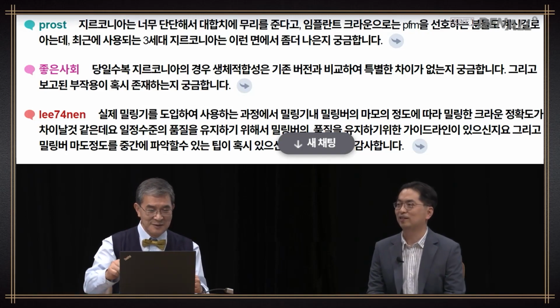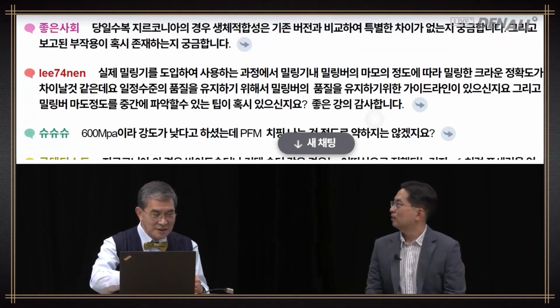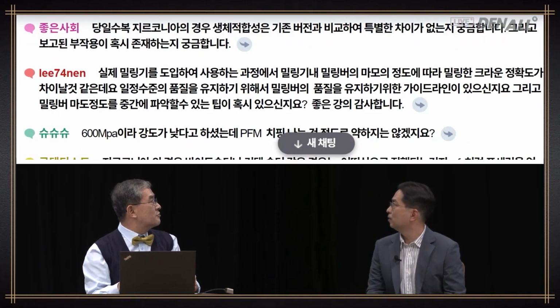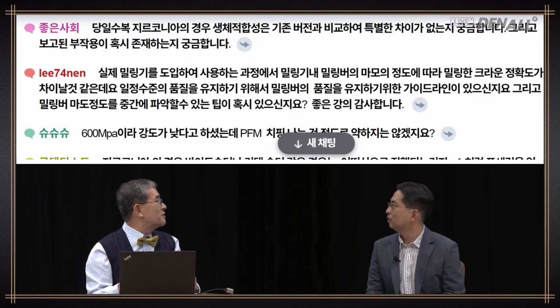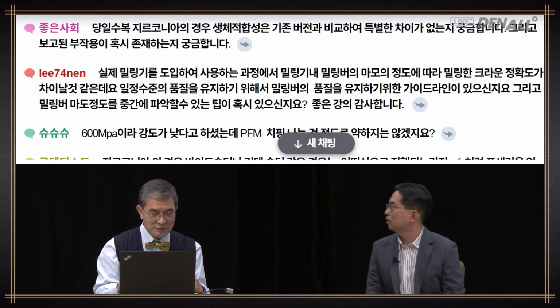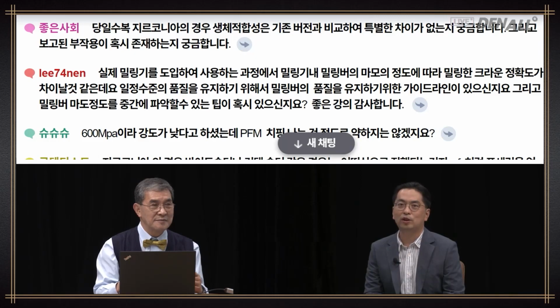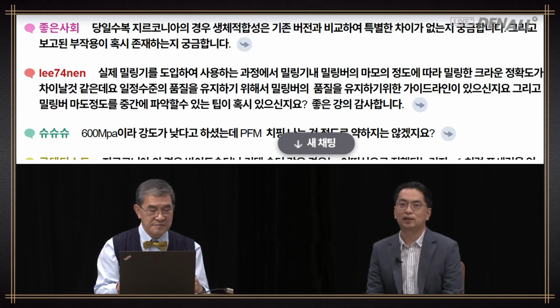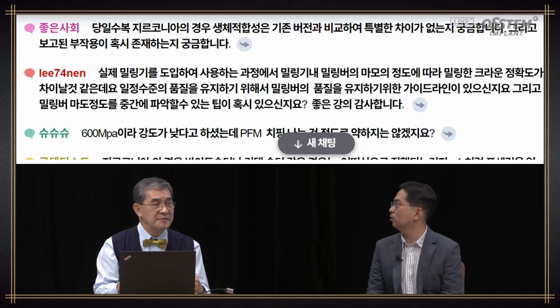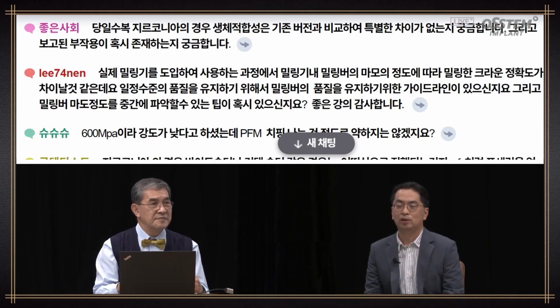Good society: in the case of same-day zirconia restoration, is there any difference in terms of biocompatibility with existing zirconia? Are there any known side effects? Once zirconia reaches a certain density with sintering, it does not show major difference. As mentioned, the commercialized 1-day zirconia has been with us for over 11 years, and a lot of research has been conducted. There has not been any special differences, so therefore you can use it in your clinical practice without worrying too much.